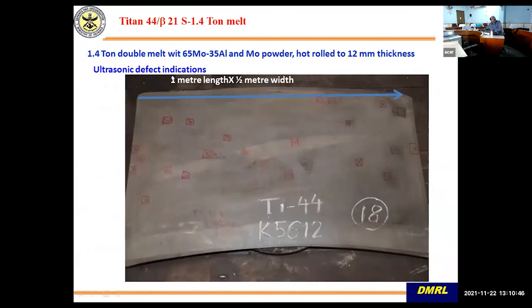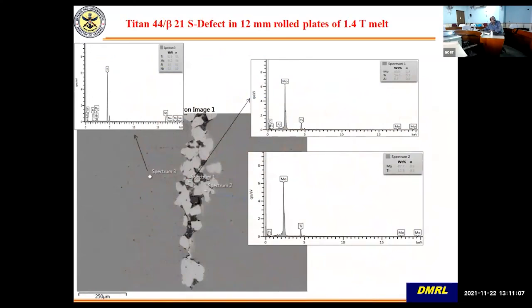But when we started melting on industrial scale, we did not get that 85 moly 15 aluminum master alloy. So we had to go for this master alloy, which was only available as 65 moly 35, and we had to use a lot of moly powder. And this ingot was processed to 12 mm thick, and then we started getting ultrasonic signals of defects. When we cut and saw, we could see unmelted moly surviving even 2 VAR melts. So moly did not melt.